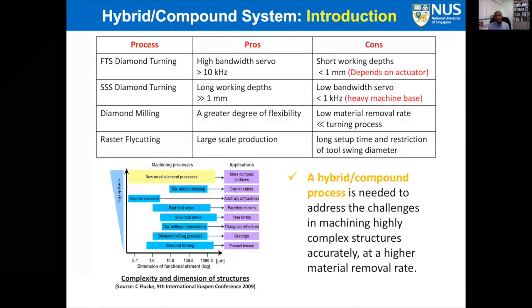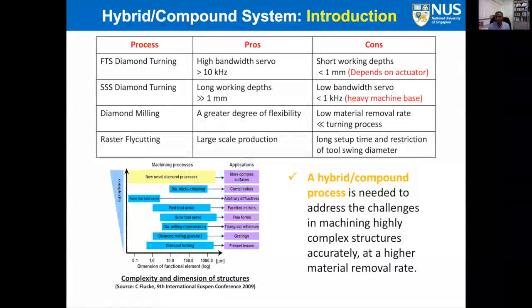When we talk about fast tool servo diamond turning, the biggest advantage is that it is a very high bandwidth servo, with a frequency of more than 10 kilohertz. The problem is that it has a very short working depth, less than 1 millimeter, and that too depends on the type of actuator. For example, if you use a piezo actuator, the travel length is much less, in the order of tens of microns maximum. In the case of slow slide diamond turning, the advantage is that it has a long working depth, but it has a low bandwidth servo, less than 1 kilohertz.